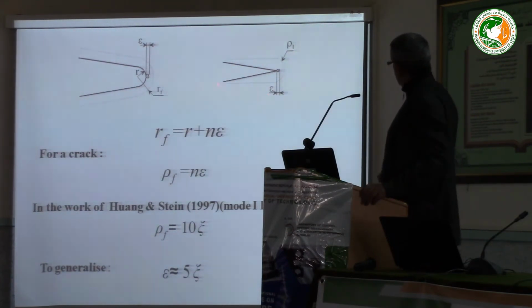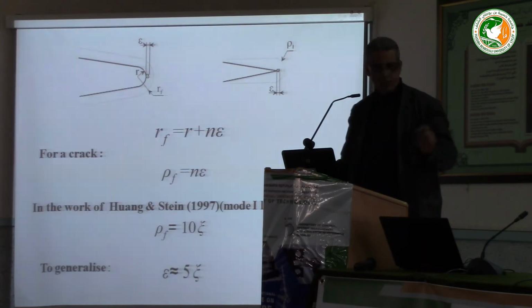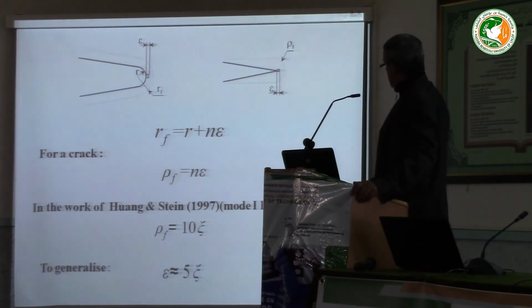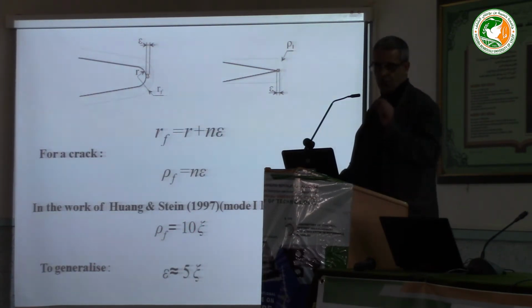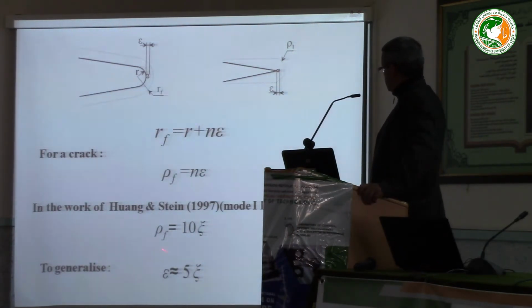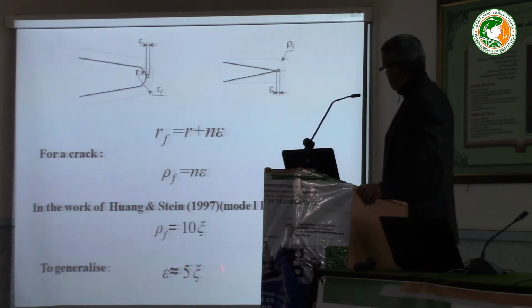Reduced in function of epsilon, which is the notion of the Neuber material. A work of Huang and Stein used this radius, 10 times the grain size of the material. To generalize, we use this block of material equal to 5 times the grain size.